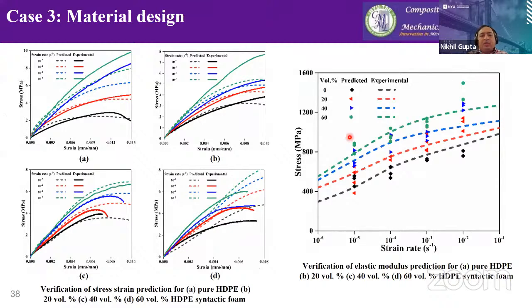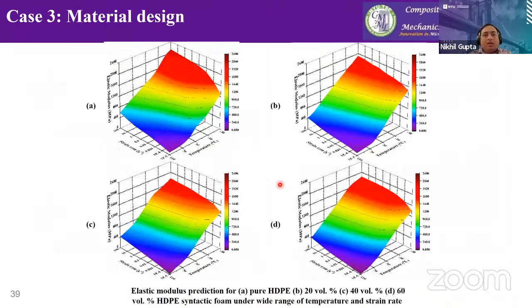So a number of different materials here, different volume fractions of particles in this material. This is a particulate composite, syntactic foam. And you can see the data matches pretty well with our predictions, more or less. The predictions start to deviate when you go to higher strains, simply because the viscoelasticity at those strains actually changes to nonlinear viscoelasticity, for which these equations are not yet designed. But that would be the next thing to do in our case. So these are the materials characterization charts that we have developed based on the scheme like that.